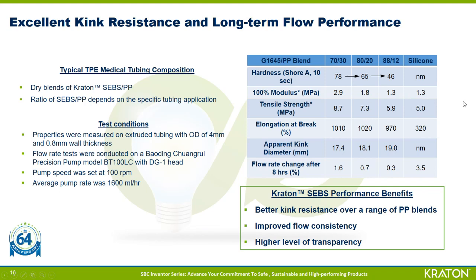tubing. In tubing application, kink diameter becomes very important. And here we can see that the apparent kink diameter of G1645 polypropylene blends is quite low. You may know that silicone has poor kink properties, and the G1645 polypropylene blend shows really improved kink resistance over silicone.